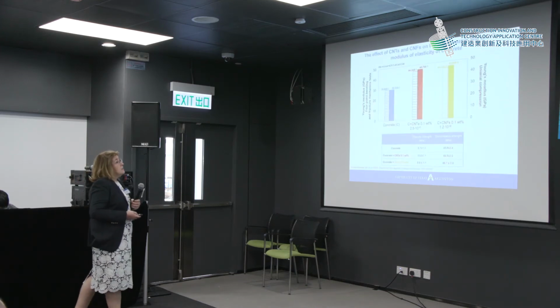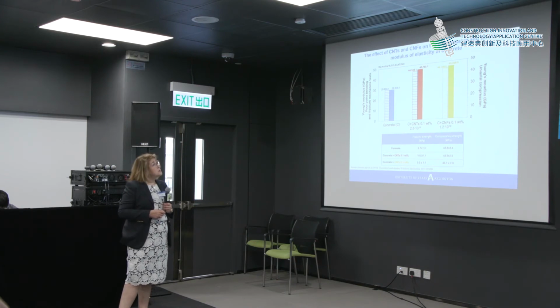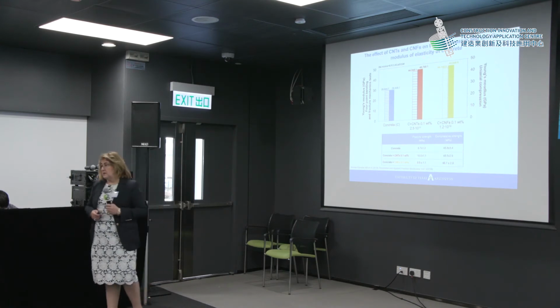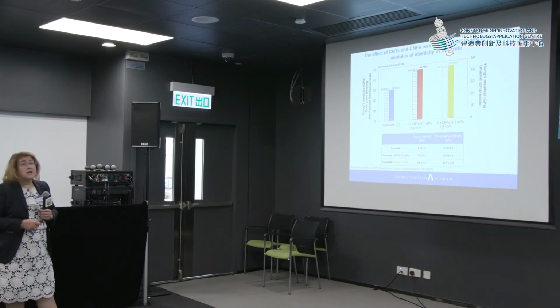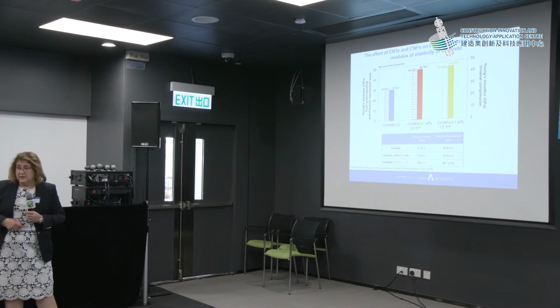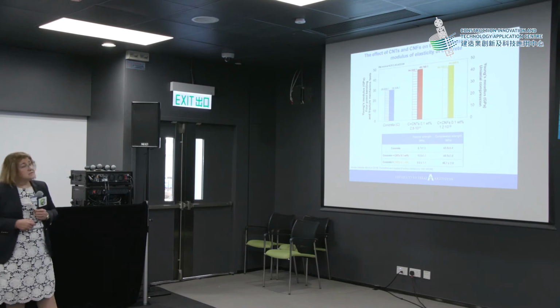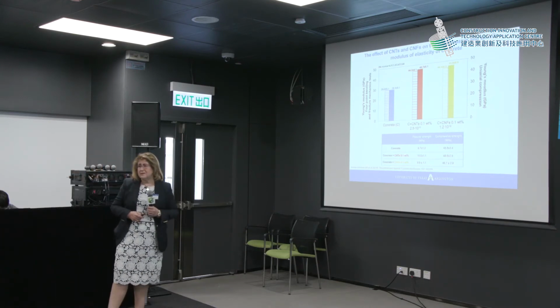and this doesn't work to our benefit. So what can we achieve by using carbon nanotubes and carbon nanofibers in concrete? Actually, carbon nanofibers are even better than carbon nanotubes in terms of the structural properties, because they are longer and they give us the advantage of a fiber. While carbon nanotubes sometimes can be really small and they do not give us the advantage of a fiber, they give us the advantage of a nanoparticle.